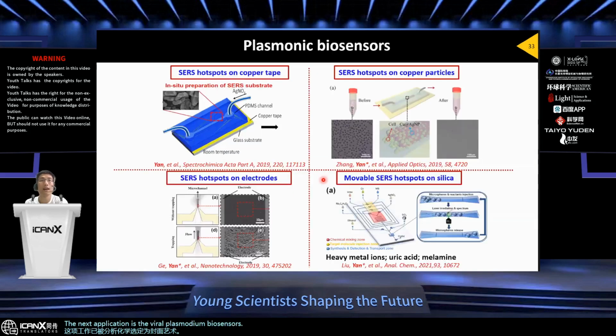Here we use the surface enhanced Raman scattering for the measurement. Previously, we can generate the SERS hotspot on the copper tape, on copper particles, or we can use the dielectrophoresis to manipulate the silver nanowire, and then we can assemble the SERS hotspots between microelectrodes. Recently we also can generate the SERS hotspot on the silica.